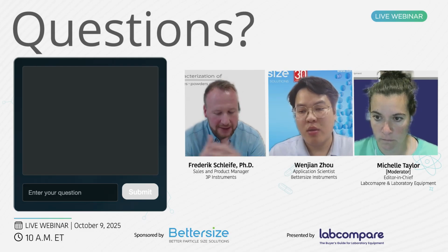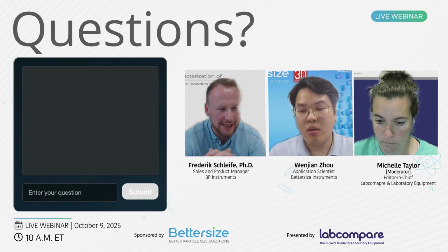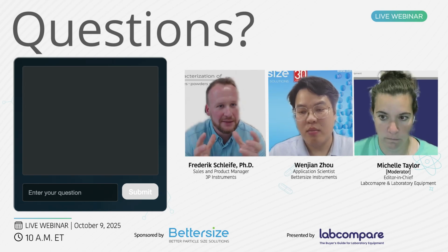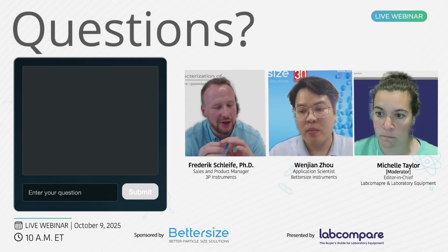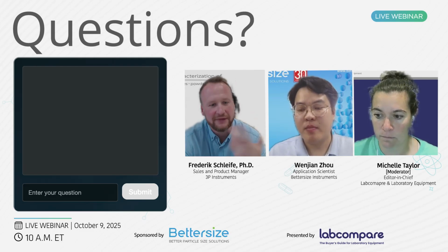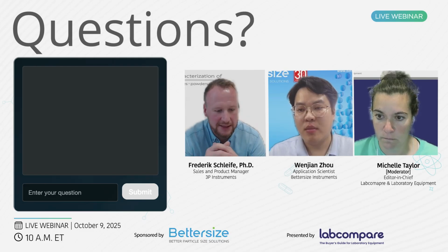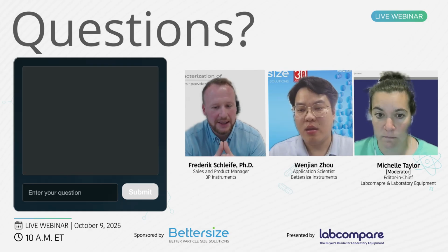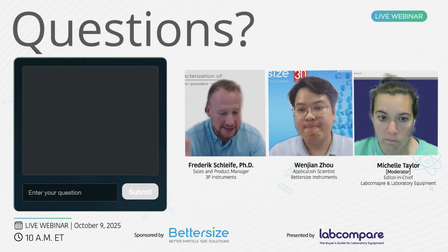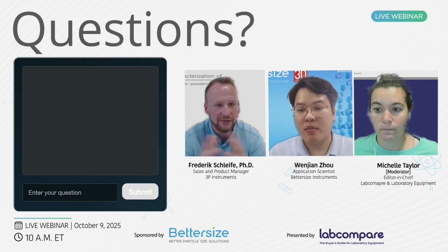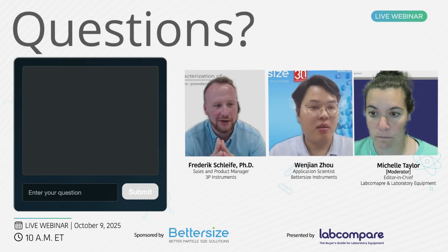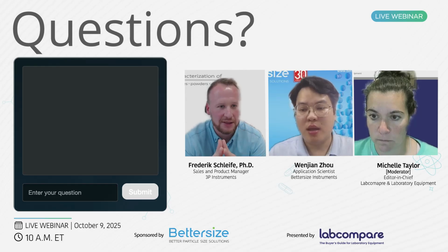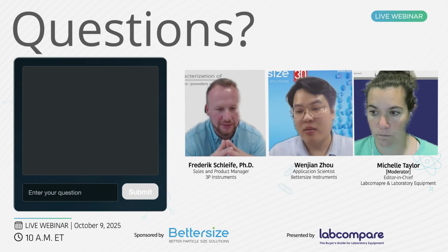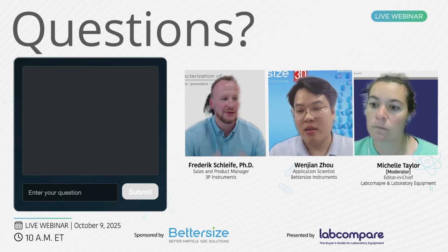So there, the image analysis could additionally help. And furthermore, a limitation in laser diffraction is that all particles are treated as spherical, even if they're not. So if you have really shape-anisotropic particles, you would not see this. Here again, image analysis can help. But on the other side, laser diffraction is pretty fast and it gives a wide range, so it's pretty popular. But sometimes, especially for unknown samples, you might need some additional information from image analysis. So this combination, Bettersize 2600 with PIC 1, is a good fit, especially to give you a deeper look inside.